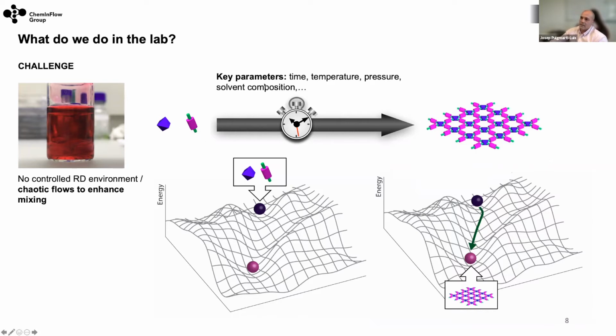And then if this does not happen, we will start to change parameters like time, temperature, pressure, solvent composition, and if this does not work, then what we will do is we will change the monomers and we will redesign them in order to achieve our expected goal. And here, playing with these conditions, what we normally achieve is the most thermodynamically stable product. We isolate the product that is more thermodynamically stable.